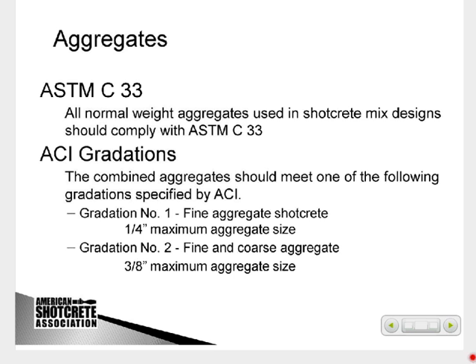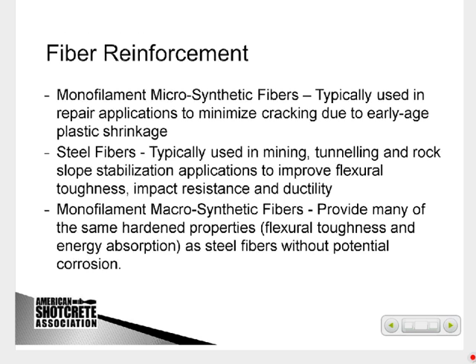We use standard aggregates. I mentioned before, we tend to limit our coarse aggregate to no more than 3/8 inch. ACI 506 has a couple gradations, both a 1 and 2. 1 is a fine aggregate only. The 2 gradation is a 3/8. We do use fibers. Typically, microfiber is used for control of early age plastic shrinkage cracking. Then if you're looking for toughness and impact resistance, we do tend to go to steel fibers or longer macro synthetic fibers.